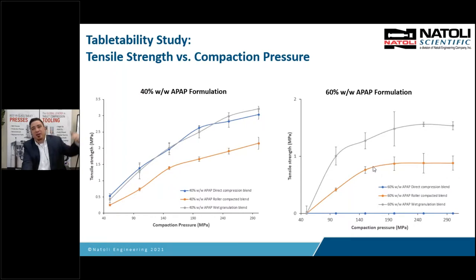So as a formulator, I would not want to be running in this range. I would tell my scale-up group, we need to be down here where it's linear. Well, they might say that's not enough hardness or enough tensile strength. Well, then we have to reformulate. But the point is, you want to be on this linear portion when you're scaling up, because if you're close to this plateau, this is where you're going to see all kinds of compression problems.